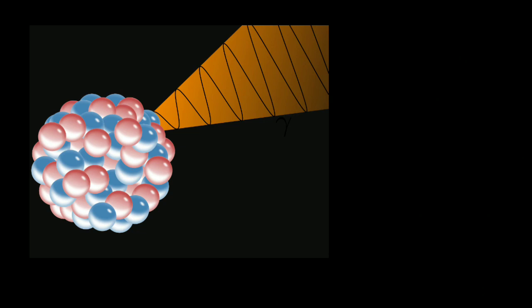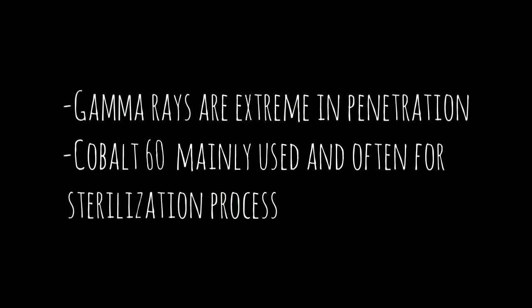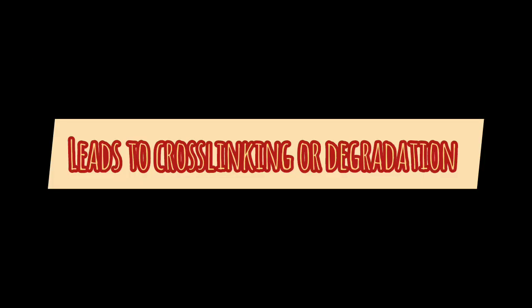When it comes to industrial use, gamma radiation and electron beams are generally involved. The reason for gamma radiation is that gamma rays are extreme in penetration, and cobalt-60 is mainly used, often for sterilization purposes. Unlike gamma radiation, electron beams have a limitation in penetration. When radiation is exposed to high polymer, different reactions may occur. There are four: abstraction, recombination, disproportionation, and polymerization. The effect of radiation leads to cross-linking or degradation of the chemicals.